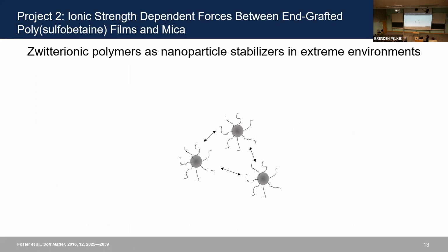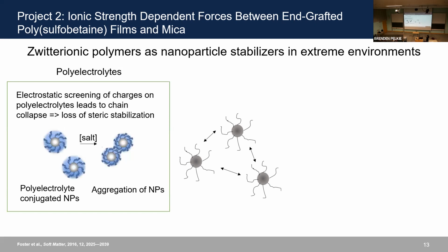Then moving on to the second part of the project, I was interested in how the ionic strength dependent swelling behavior affects the surface forces of grafted zwitterionic polymers. The motivation for this project is that zwitterionic polymers very effectively can stabilize nanoparticles in high temperature and high salt concentrated solution. Polyelectrolytes are not an ideal choice because, with salt present in the surrounding solution, there is electrostatic screening of the charges of the side chains of the charged polymers. And so that leads to a collapse of the chain, and there is loss of steric stabilization. So the nanoparticles would aggregate.